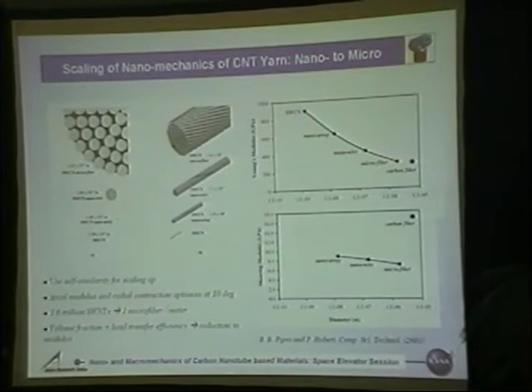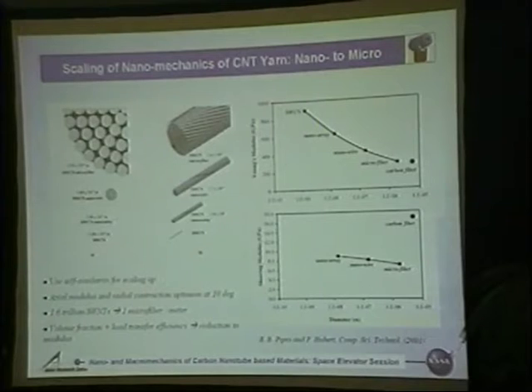So the scaling law is that I take this nanoscale fiber, twist them into a yarn, then take this yarn and again have a collection of them and twist it into a bigger fiber, and then have a collection and twist into a bigger fiber. So there is something called use of self-similarity for scale. But at each scale, when we are mixing these things up, the volume fraction is going down by 20%. So here you see this is single wall nanotube, this is a nano yarn, which they did in the experiment, and this is a micro scale fiber, which you can have at 50 to 100 micron diameter. So this you can handle.